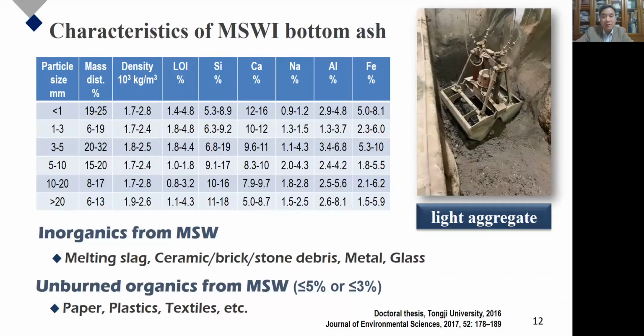According to the standard for pollution control under municipal solid waste incineration, the loss of ignition for bottom ash should be no more than 5%. And in some cities, such as in Shanghai, the limit value is 3%. This table shows the particle size distribution of bottom ash, together with the density and the main chemical components in the bottom ash with different sizes, which are similar to natural aggregates. Therefore, bottom ash has great application prospects for valorization in construction.